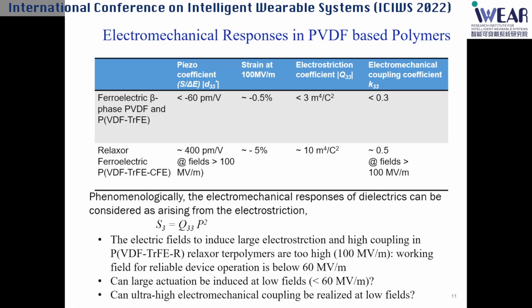From the device work, what they told us is the device can only be operated below 60 megavolts per meter if you want to use them for a long time. So we are asked by various end users, can large actuation be generated at a low electric field, less than 60 megavolts per meter? And also, can high electromechanical coupling factor be realized at low field? They say you can get 0.5 coupling factor. Can you get even higher?